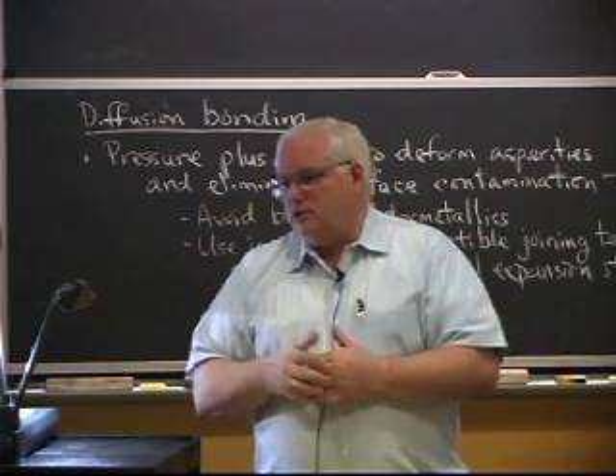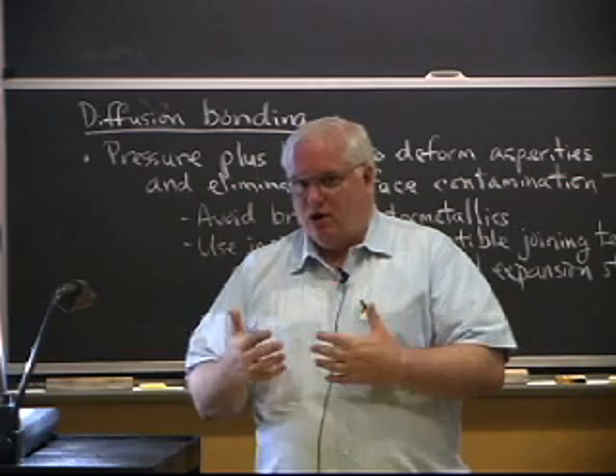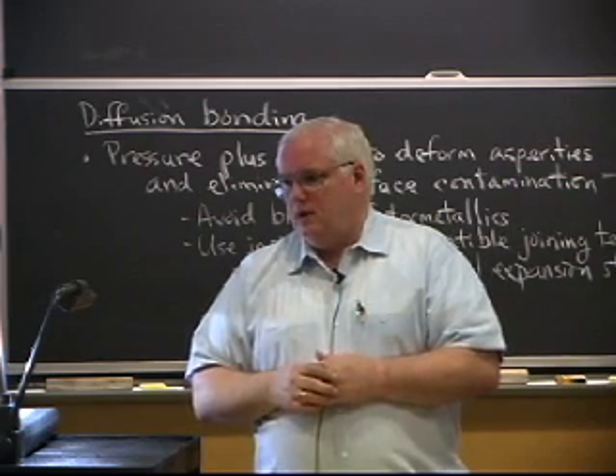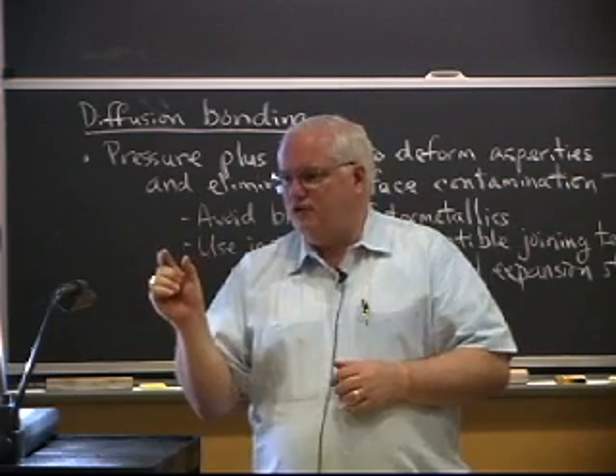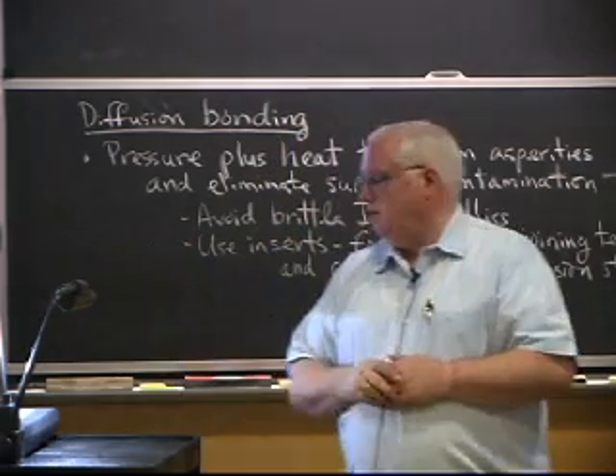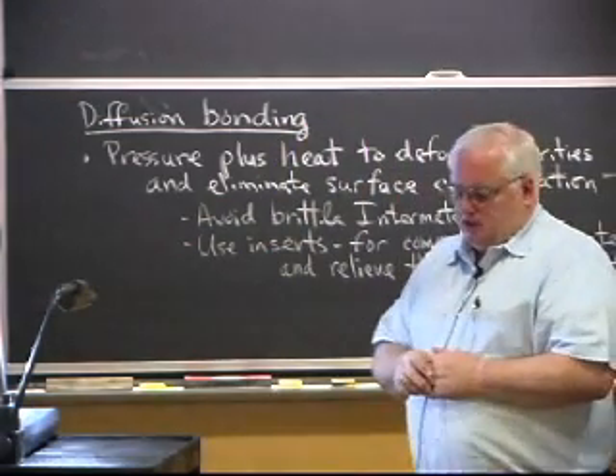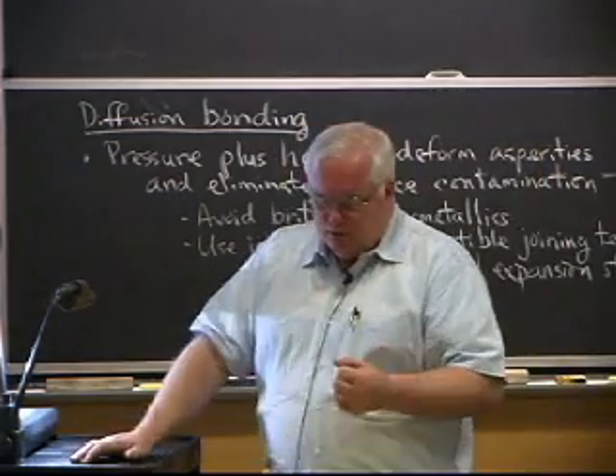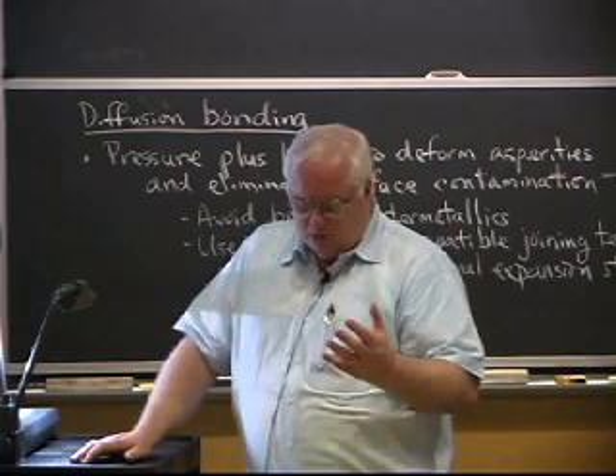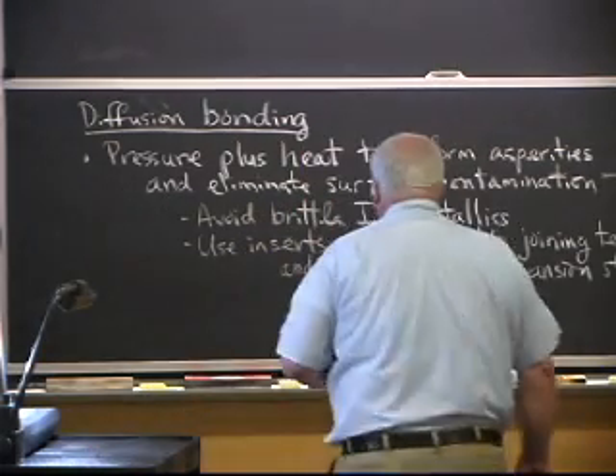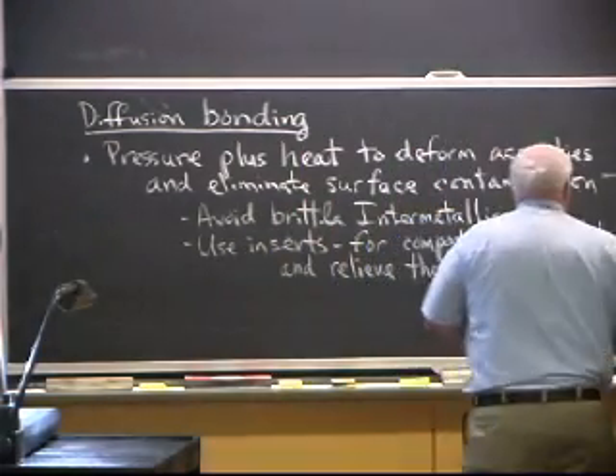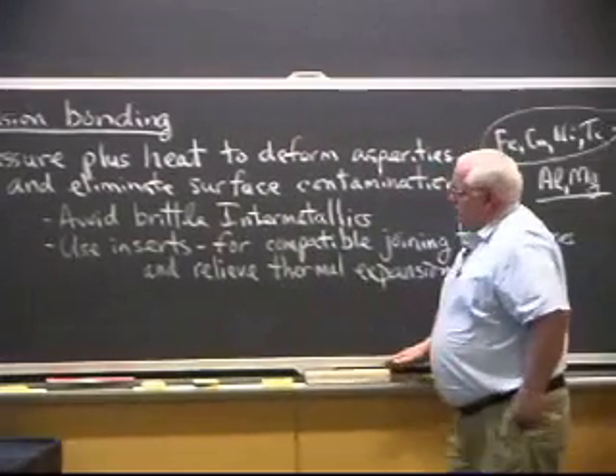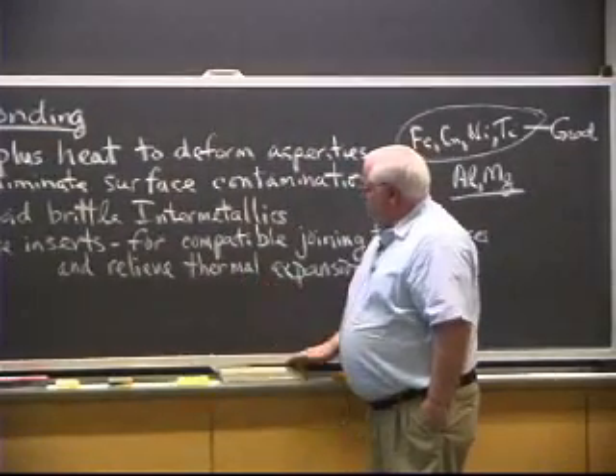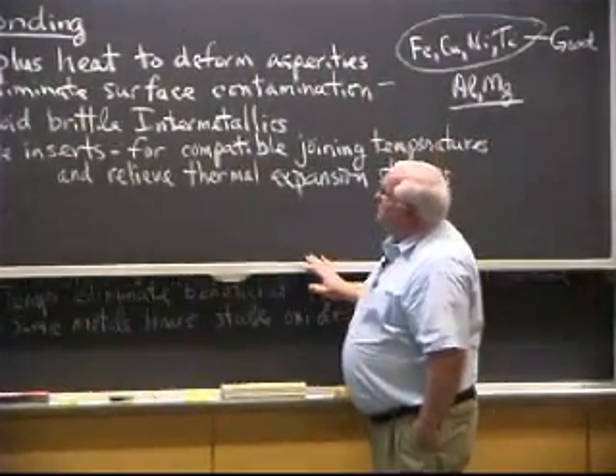And so one of the things they make nowadays is silicon carbide aluminum composites, which you can match the coefficient of thermal expansion of that to the silicon and end up without the big problem. And you've got aluminum, not quite as good as copper for pulling heat away, but not bad. And it turns out silicon carbide has reasonable thermal conductivity as well. So you can put inserts in between to relieve residual stresses.